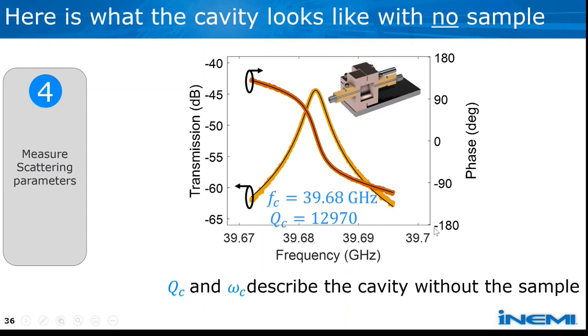So when you have a resonator that's a little bit below resonance, you have a positive phase shift relative to the resonator. That's what you're seeing in the orange line right there. And then as you go through resonance, the phase shift relative to the resonator is 0. And then as you go a little bit higher than the resonance, you get a negative phase shift. And so you can see that there's a peak in the transmission at the resonance frequency. And all we're going to do is measure that resonance frequency, f_c, and Q_c. And sometimes we'll write the word omega_c. That's just 2 pi times f_c. That's the angular frequency right there. So we're just going to measure the cavity with and without the sample.